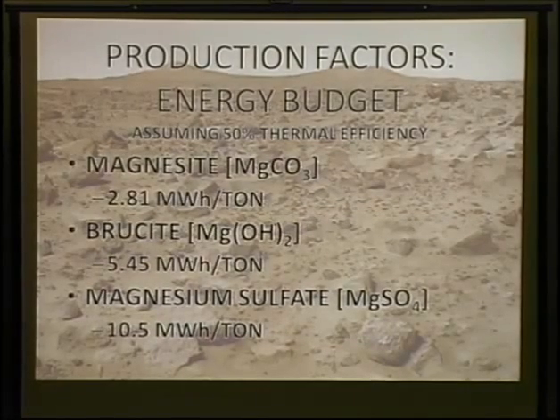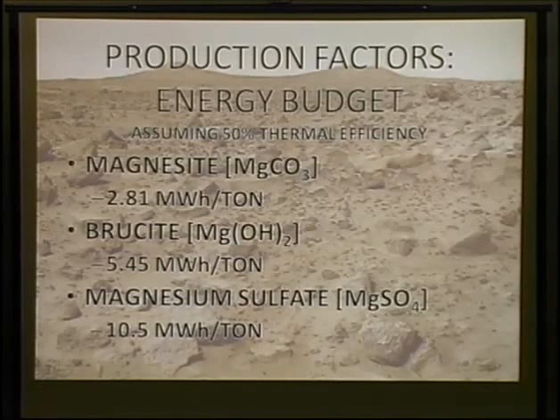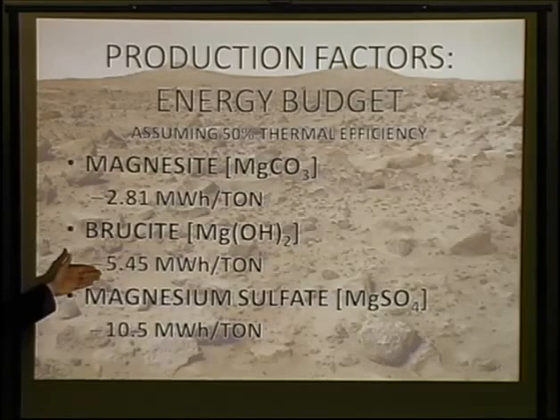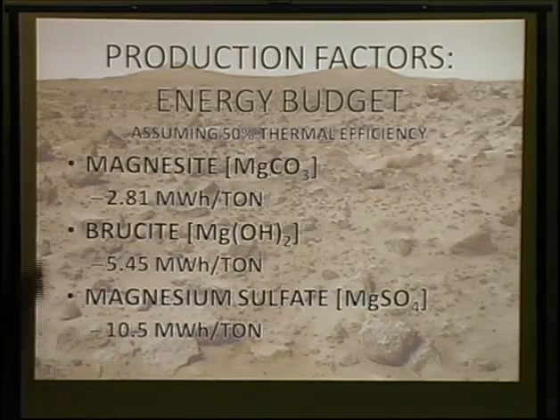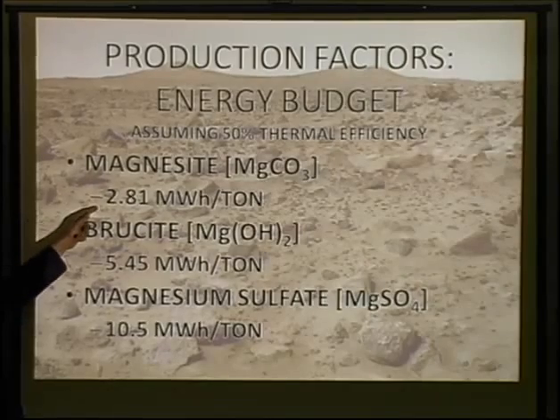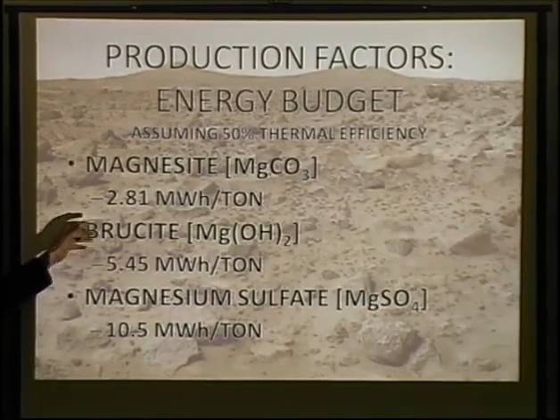Now, as far as the energy required, if we can find usable quantities of, well, I got these figures switched out. Sorry about that. Magnesite, the most common mineral, the energy requirement is 5.45 megawatt hours per ton of magnesium oxide. I got these two numbers switched. To produce it from brucite, it would be 5.45 megawatt hours per ton.